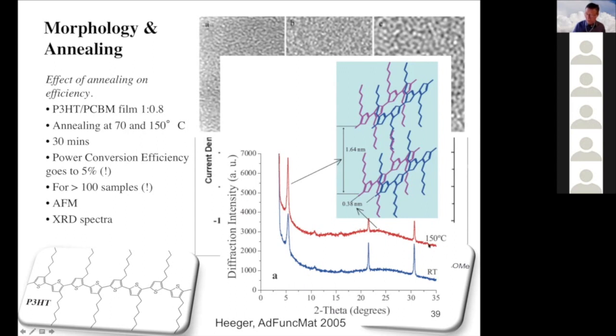Annealing your sample, heating your sample at 150 degrees for half an hour, it increases the crystallinity of the polymer domains. The polymer phase becomes more crystalline. And that is better, that is improving the device efficiency, and it also improves the charge transport. So you again see that size domain, nanoscopic domains, and molecular organization, order, that it is very important for the